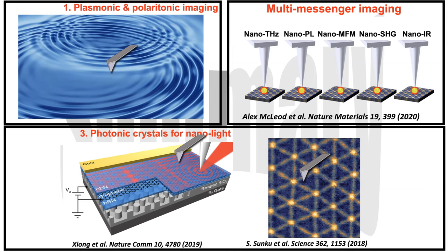Well, but I guess that is the free space wavelength. I mean, the plasmonic wavelength. Oh, I see. So the plasmonic wavelength is determined by the dispersion. The shortest wavelength of plasmons we've measured was limited by our near-field spatial resolution. That's about 20 nanometers. The wavelength of light was still about 10 microns, so we really have a pretty significant confinement of these modes. One limit is the spatial resolution of the apparatus. Another limit is that if you have very confined modes, then it has flat dispersion, so it's no longer moving. Eventually you'll run into this type of problem as well. So 20 nanometers is what we've seen.